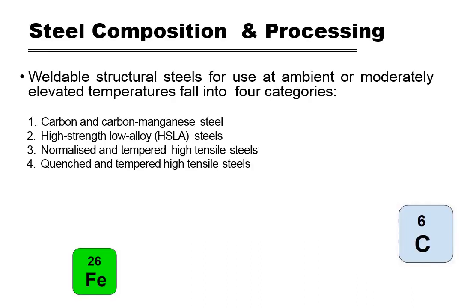Steel composition and processing. Weldable structural steels for use at ambient or moderately elevated temperatures fall into 4 categories. Key word here, structural steels. Carbon and carbon manganese steels, high strength low alloy steels, normalized and tempered high tensile steels, and quenched and tempered high tensile steels. And each one of these categories has its own nuances involved in being able to weld it and have a weld come out that meets the criteria for the weld joint and matches the base material and the tensiles and the hardnesses, and make sure you don't have a messed up heat affected zone. So, yeah, these are pretty much the 4 categories, and each one of these is a different animal. I'm not going to go into each one in detail, but we're kind of covering some of them.